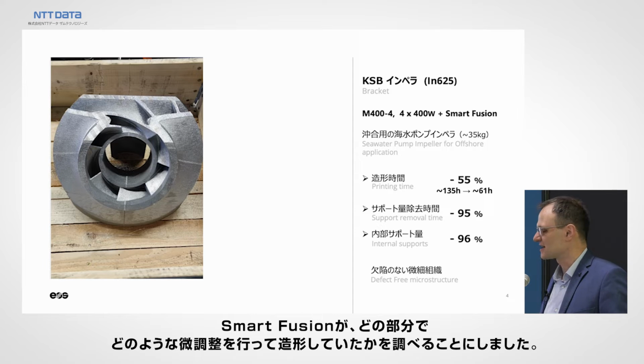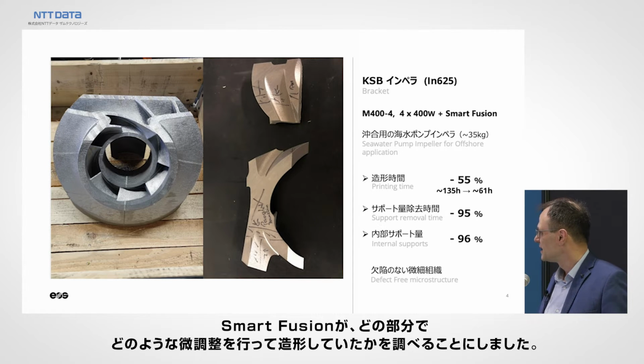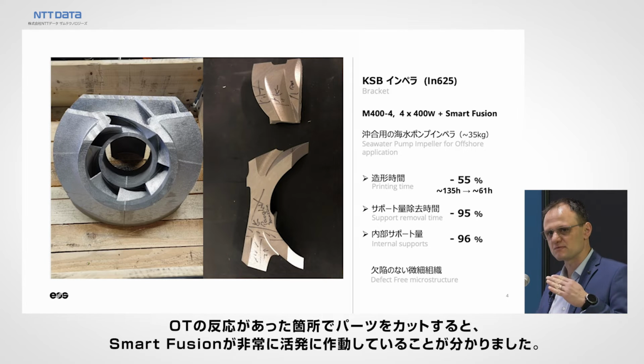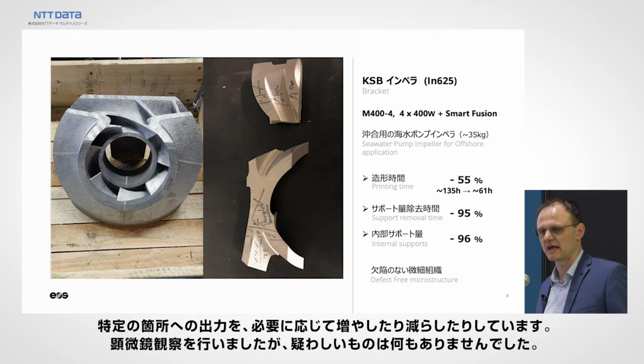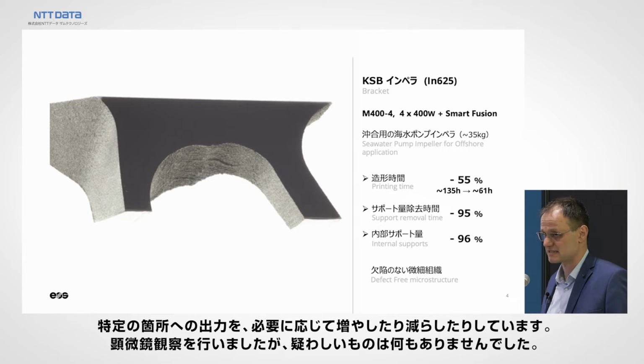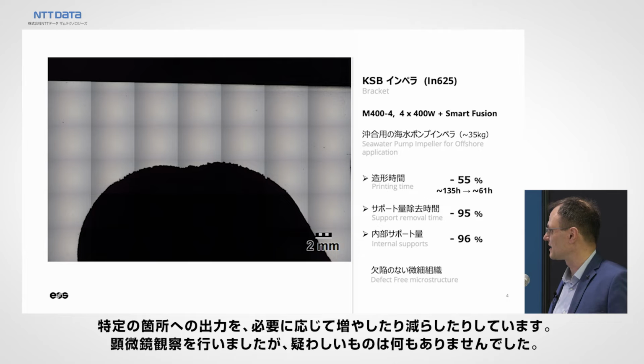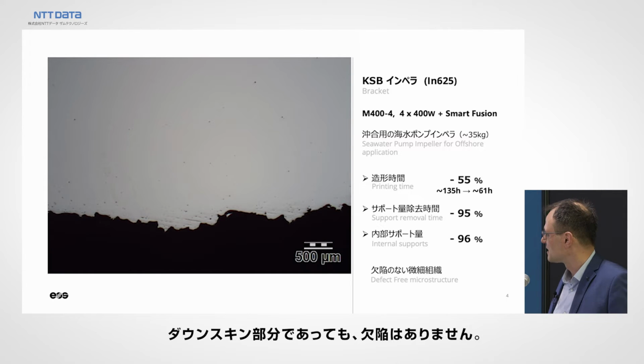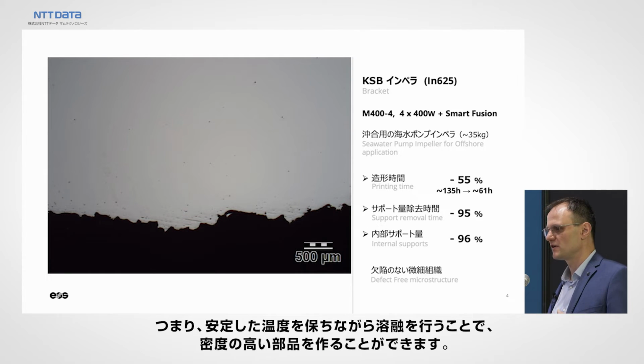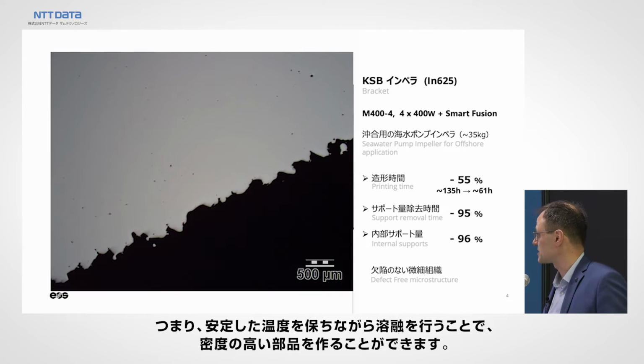Let's make the best out of it and start looking into areas of interest where the Smart Fusion parameters had to be tweaked and fine-tuned to make the part perfect. So we started to section the component into areas where we saw from the OT signal that Smart Fusion was very active and was regulating a lot, reducing the power in certain areas, or increasing the power, which can also be done where necessary, and did microscopic evaluations, and we did not find anything suspicious at all. Even in the areas where you have very high downskin areas, you don't have increased porosity, nothing. So that means our idea and the philosophy of having a stable temperature whilst melting is actually paying off to make a dense part, which is what you want to have in the end as a customer and application.